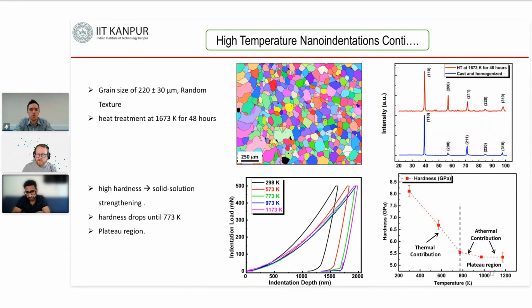Another question from Aditya here, who says, please comment on the life of the indenter against steel at 900 degrees Celsius. More like hours or minutes per contact cycle, or hours? I think more like minutes, at that temperature. The contact area is very small, so of course the geometry of the tip is very important. So any small change renders your data fairly meaningless. So I think it would not last very long at all in terms of meaningful nanoindentation.